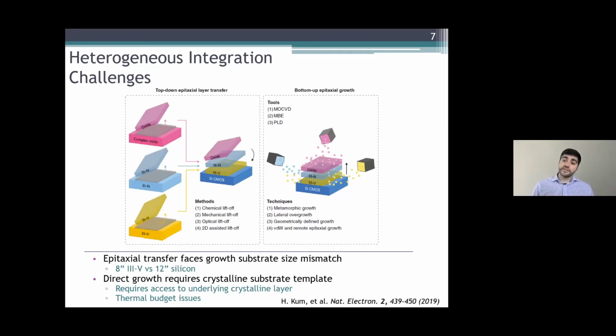There are still some challenges associated with scaling it to match silicon CMOS processing. Most of these exotic devices that we want don't have 12-inch substrates, which means you can't really get the advantages of scale of silicon processing. And that's where a lot of the cost reduction comes from when you get to this 300 millimeter process, or eventually even larger. On the other side, you can do bottom-up epitaxial growth, where you take a crystalline substrate and keep growing different types of materials on top of it.